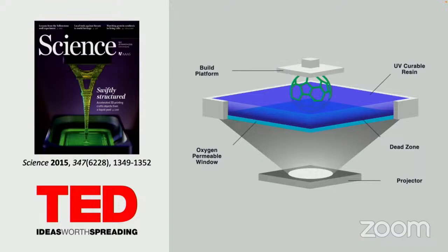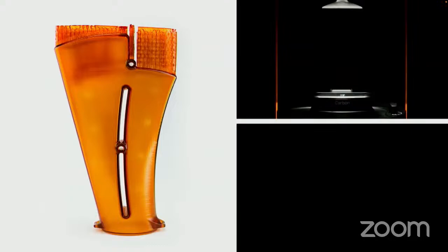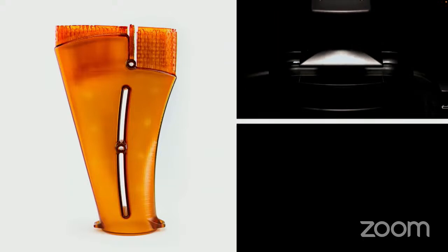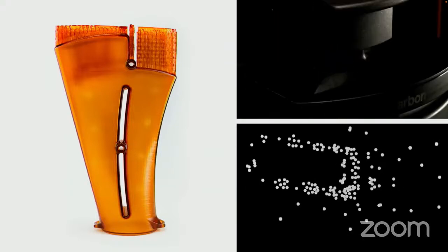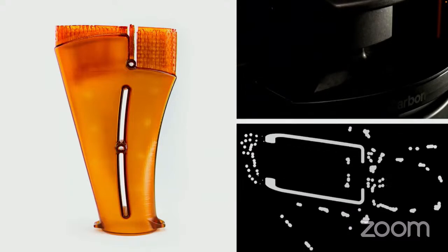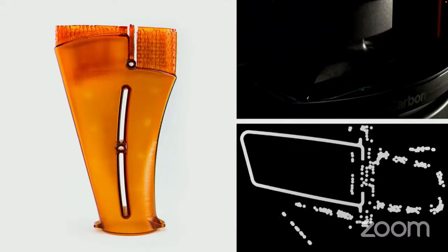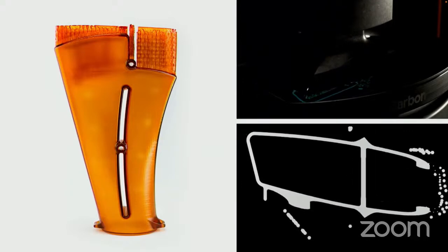Here, we're exploiting oxygen. We're exploiting the inhibition of the polymerization and the replenishment of oxygen caused by the depletion of oxygen with the light-induced decomposition of the photoinitiator. I'll walk through that in more detail. So what happens is you lower this platform into this liquid reservoir, you get very close to the window, and let's say you get close to about 100 microns. So you have a 100 micron sandwich of UV curable resin between this stage and the window, and then you start projecting light. And what happens is that light will permeate that 100 micron gap, will cure the resin asymmetrically.